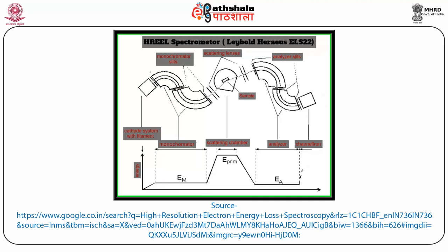In the scattering process at the sample, the electrons can lose energies from several 10 to the power minus 2 electron volts up to a few electron volts. The scattered electron beam, which is around 10 to the power minus 3 lower in flux than the incident beam, enters the analyzer; another CHA is there for the analyzer. The analyzer CHA again allows only electrons of a certain energy to pass through to the analyzing unit, a channel electron multiplier, abbreviated as CEM.